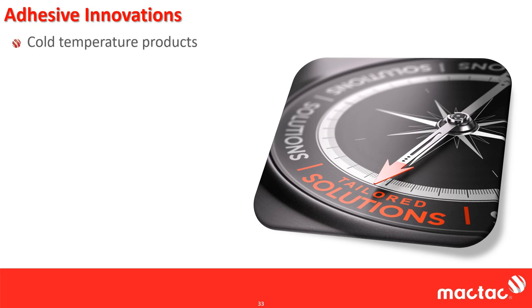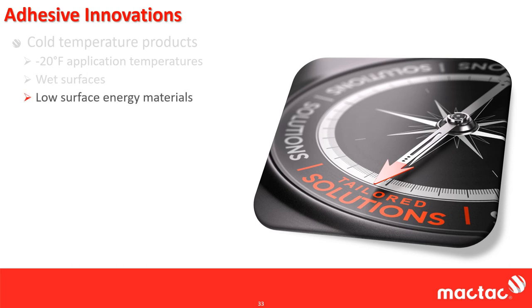We have a new line of cold temperature products, and they feature an adhesive that will adhere down to negative 20 degrees Fahrenheit. It will also adhere to wet surfaces and low surface energy materials, and it will adhere to wet low surface energy materials that are at negative 20 degrees Fahrenheit. These are the three worst case scenarios for an adhesive tape, and we solved all three simultaneously with one product.